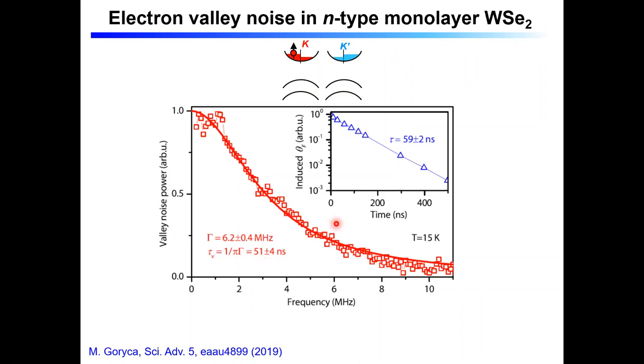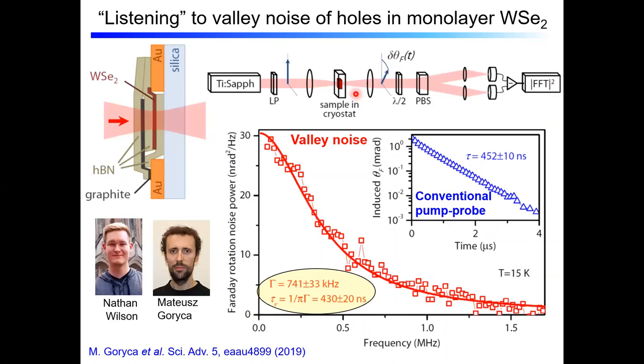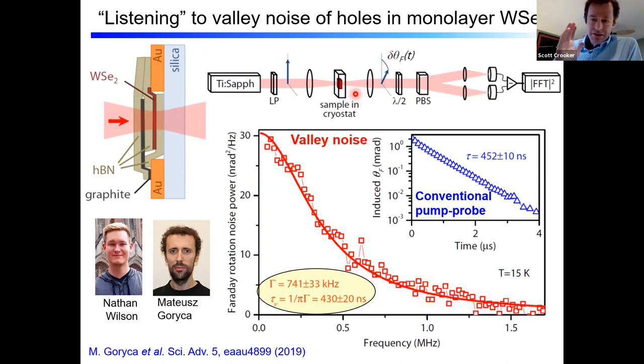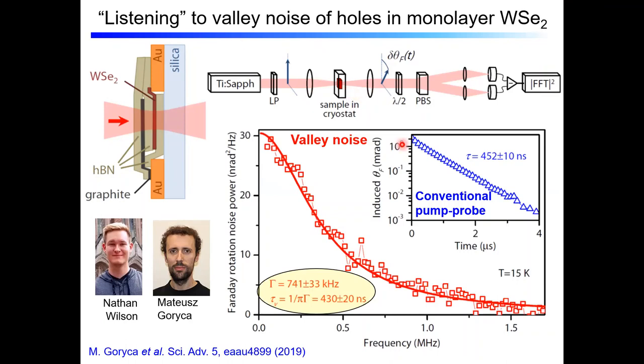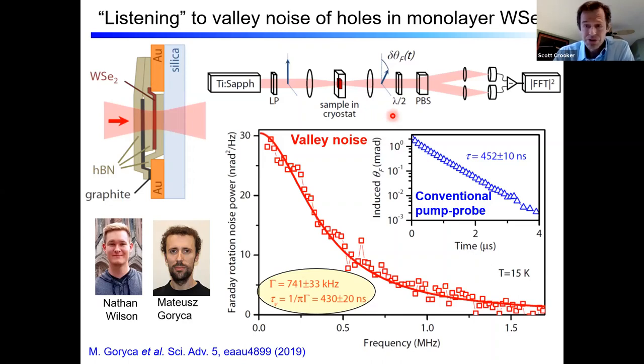So Scott, just to be clear, in your noise measurement, you do not first pump excitons to let them decay. You are looking at a basic equilibrium already doped sample, that's it. Yep, exactly. That's exactly the main point in all of these noise measurements: we never pump it. So it's guaranteed, 100% certain, no weird dark exciton effects. This is really and truly the intrinsic response. Although your measurement light is still close to, does it self-excite excitons or is it sufficiently far away? It doesn't. Excellent question. This is something we always worry about in a noise measurement. I can show you a spectral analysis and a probe power analysis that proves that the interrogation light itself is not perturbing the system, but that's always something that one has to worry about.